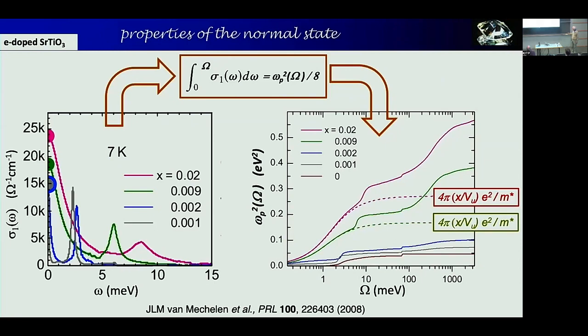So if you know the Drude peak and you extrapolate the tail, you can integrate the spectral weight in this Drude peak. It's done over here. This is the integrated spectral weight as a function of frequency. It sort of saturates, but then of course you hit also this phonon, as I already said, and you get other things up there. But if you just extrapolate it as it would be for a Lorentzian line shape, then this area, the spectral weight, corresponds to something that's proportional to the doping, this x, over the unit cell volume times the electron charge squared, divided by the effective mass of the particles that form this Drude peak. And this is for different dopings here.